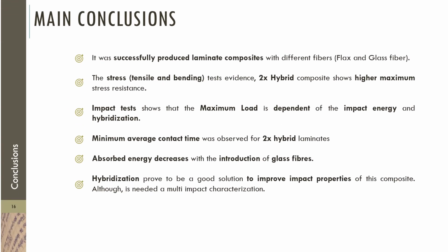So we can conclude that we successfully produced laminate composites and hybrid laminate composites with different fibers, flax and glass fiber. We can also conclude that the stress tests evidence that 2x hybrid composites have higher maximum stress resistance, both for tensile and bending stress tests.